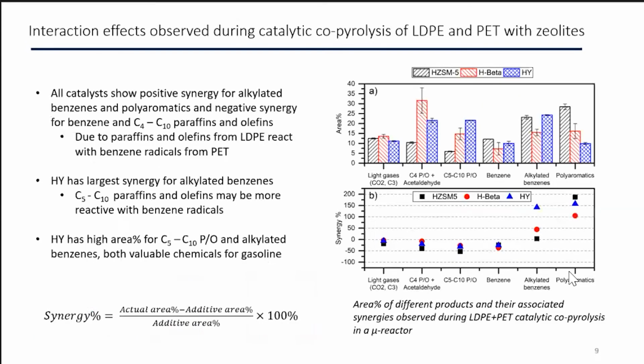So now that we've done these single stream experiments for the product characterization, we were able to do the catalytic co-pyrolysis. And we were able to compute an additive area percent. And from this, we're able to calculate what is called a synergy. And this positive synergy percent is saying that we saw a higher area percent for these products than would be expected from the single stream experiments. And what we saw was that for all of our catalysts, there is a positive synergy percent for both the alkylated benzenes and the polyaromatics. And there is a negative synergy percent for the C4 to C10 paraffins and olefins and for the benzene.